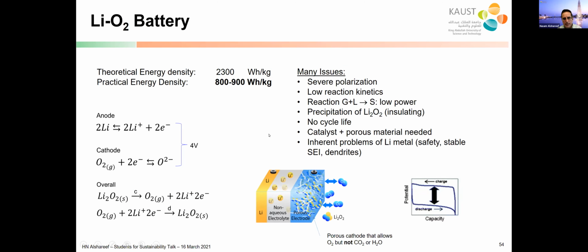Lithium oxygen battery, again, this in principle can give you 800 to 900 watt-hour per kilogram, but it also is plagued by severe problems, a lot of problems, like polarization is high, it's not so reversible, it has low reaction kinetics, poor cycle life, and so forth. That's another one you hear a lot about, but the truth is that it has a lot of problems yet.